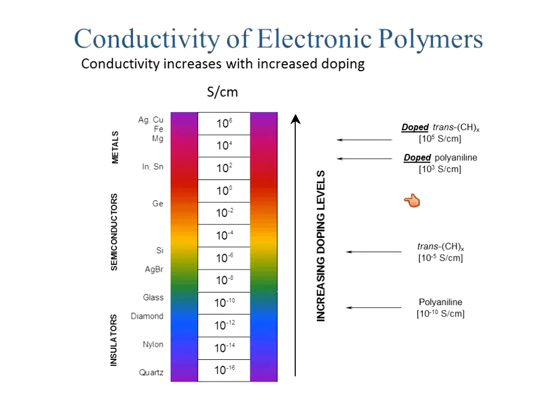The key thing is that conducting polymers, first of all, you can synthesize them in the lab. That's important. They're cheap, they're flexible, they can be made transparent, and most importantly, they can be doped. For example, you see here polyaniline in the emeraldine base form, the insulating form, has a conductivity of 10 to the minus 10 Siemens per centimeter. Then you can dope it up to 1,000 Siemens per centimeter. So you can control the conductivity of polyaniline anywhere in this range, something that you would not be able to do with a metal.